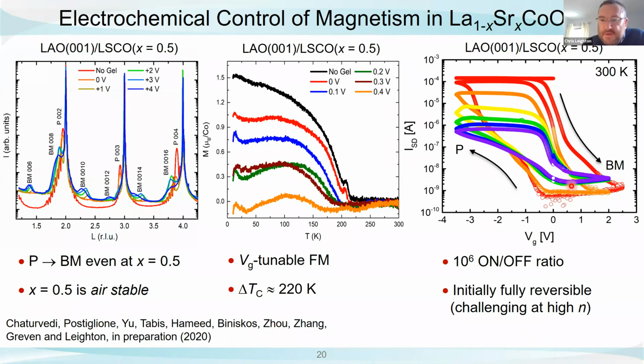We see specifically that it's relatively easy to go to the brownmillerite, but it can become progressively more difficult to get it back to the fully oxygenated perovskite. There are some strong hints in the synchrotron X-ray diffraction data about why that might be, and this is something that we're working on in my group actively right now to try and understand the details of that process. But hopefully this certainly shows that we can make quite radical variations in the magnetic property of a material happen using electrochemical gating in this kind of technique.